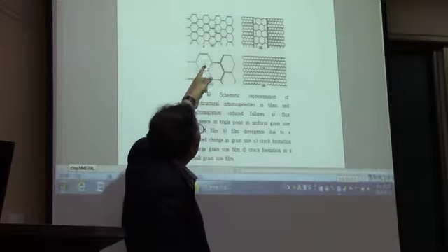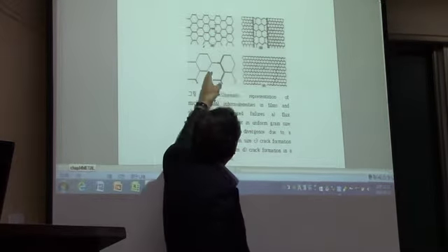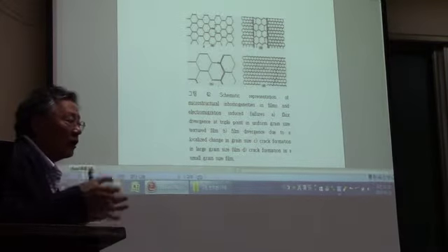Now, if you have a uniform grain size in your metals, of course, there is a triple point which is related to electromigration as a depletion or accumulation of atoms. And the triple point is very much dependent on the grain size. If you have a large grain size, you have a large accumulation, large depletion, things like that, compared to a small grain size.